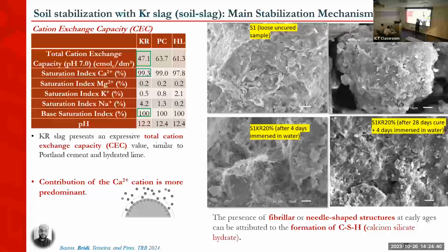He also saw that the contribution of the cation Ca2+ was more predominant, and this cation can exchange more easily with clay minerals and give the positive results of flocculation and agglomeration that we expect when we stabilize a soil with calcium-rich material.